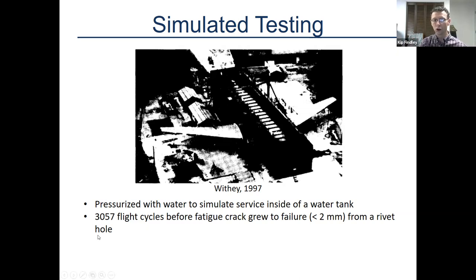And ultimately what they found is that there were about 3,000 flight cycles before they found a fatigue crack. And a fatigue crack grew less than 2 millimeters before the plane failed. So this is a real challenge, right? You have to be able to detect a crack that's less than 2 millimeters in size before the plane actually fails. And that's pretty tiny. I don't know what you think, but that's pretty tiny. And I guess importantly, it failed from a rivet hole.